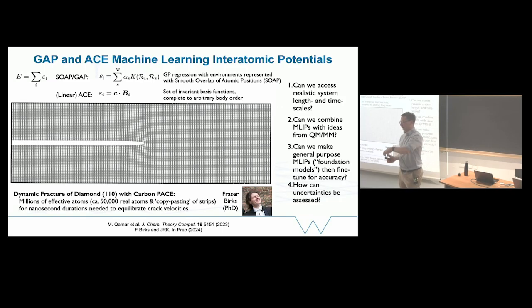I don't think I have a movie, but if you take a perfect crystal and you pull, you will initiate voids in there at some point. But on the simulation timescales that we can access, your strain rate would be much too high, orders of magnitude too high compared to experiments. So that's a harder problem. We need rare events for that. So we'll come back to that one.